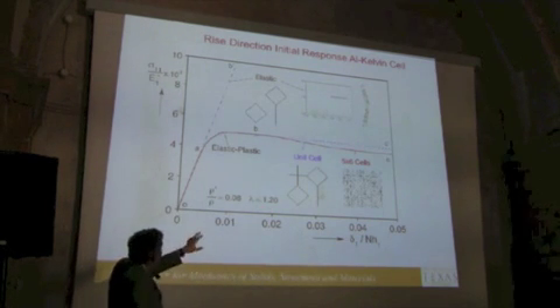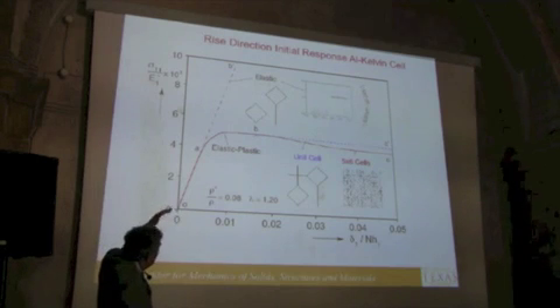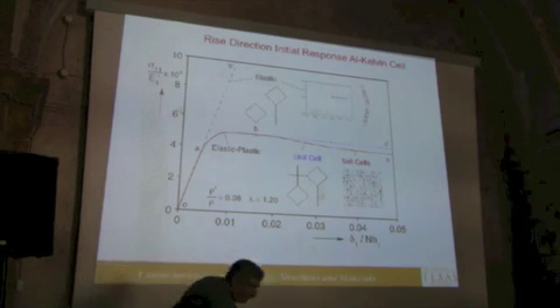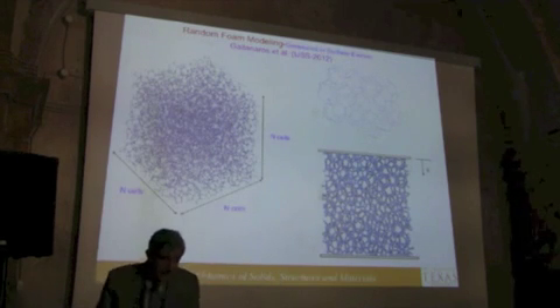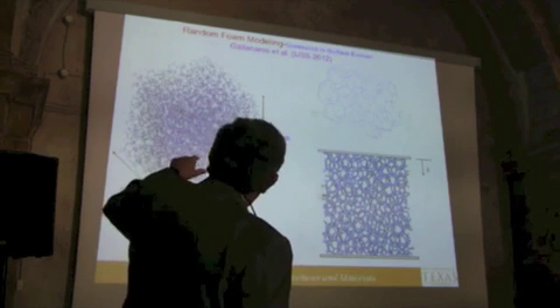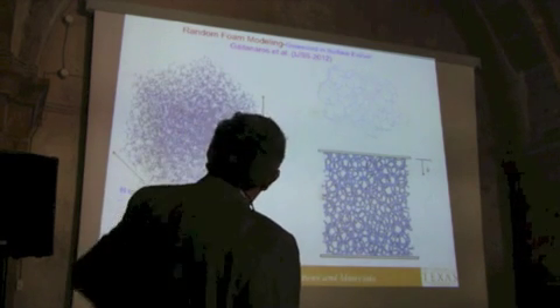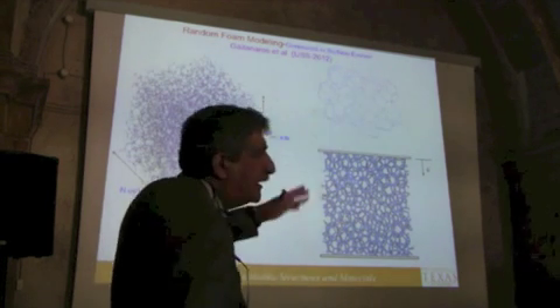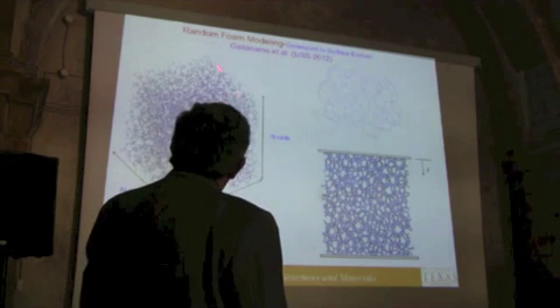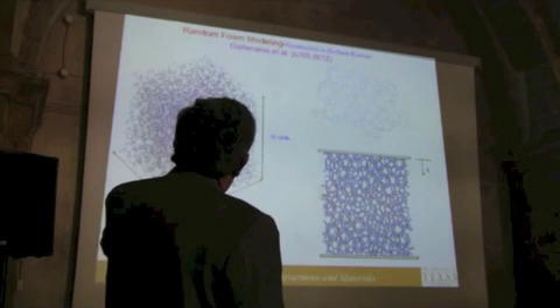That's the extent of homogenization that has been done in these problems. But like I said here, you analyze one cell and that's the dominant behavior, and you get this limit load, and that's the strength of the material. If you want to get the plateau and the extent of the plateau, then in our case we had to work much harder. And instead of showing you the solution that we obtained from the Kelvin cell, I will show you more recent results where the randomness of the microstructure is introduced. This is an n by n, and the n for us here is going to be 10 or 12 cells, so it's 12 cubed, about 1,000 cells, and is generated using a program called Surface Evolver.